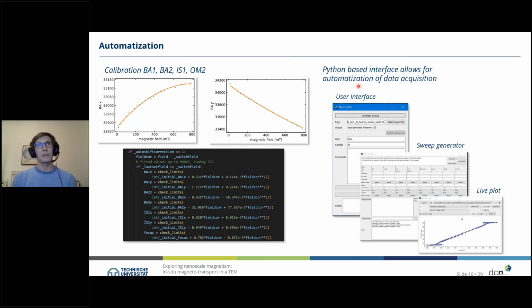Since we're changing the objective lens, and therefore also beam deflections and shifts and so on, we needed to calibrate the beam shift, which in our microscope, a JEOL F200, is called BA1. The BA2 is the tilt of the beam. We have an image shift as well, and we have a slight defocus of the focusing lens, the mini objective lens, and all of them are calibrated as a function of the magnetic field. This was done by hand, reshifting the beam, for example, recalibrating the microscope for different settings of the magnetic field value.